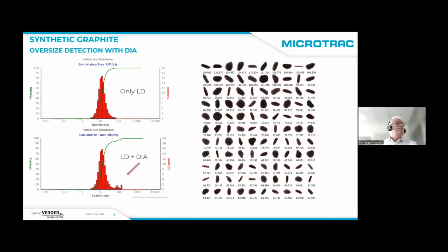And this is shown here for a synthetic graphite, for example. Only the laser diffraction gives a particle size around 10 microns. And with the dynamic image analysis, the DIA, we see some oversized particles, and you can see them here also in the pictures, 131 microns, so quite lengthy particles, 114. All these are above the optimum size for that case of 10 microns. And they will disturb the performance later on. So it's good to know these particle oversize in the production, for example, of your graphite for your electrodes.